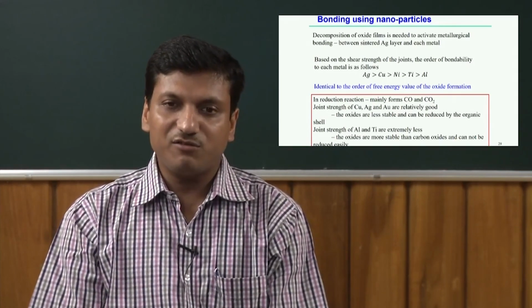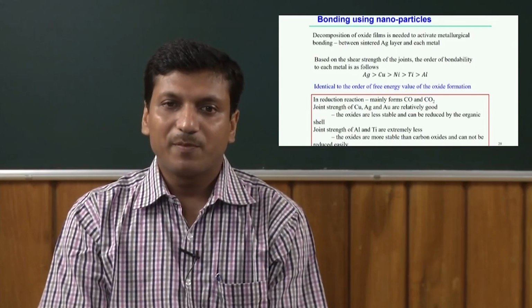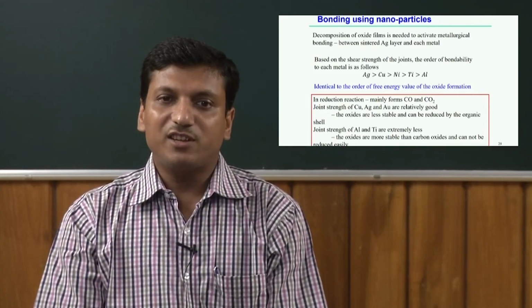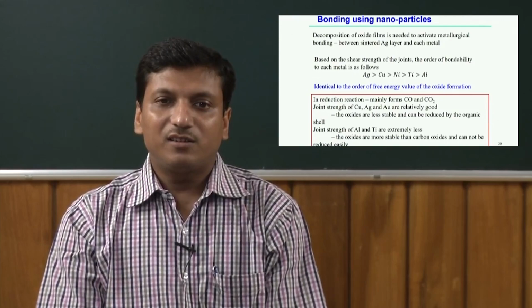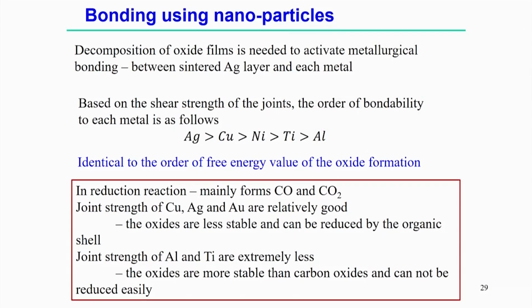In the reduction reactions, mainly CO or CO2 is formed. In this case, the joint strength for copper, silver and gold is relatively good because the oxides are less stable and can be reduced by the organic shell. This is one possible way. In the other case, for aluminum and titanium, the joint strength is relatively lower because the oxides are more stable. So it is not easy to form CO and CO2 and remove the oxide layers, and that is why bondability is not good using the nanoparticles.